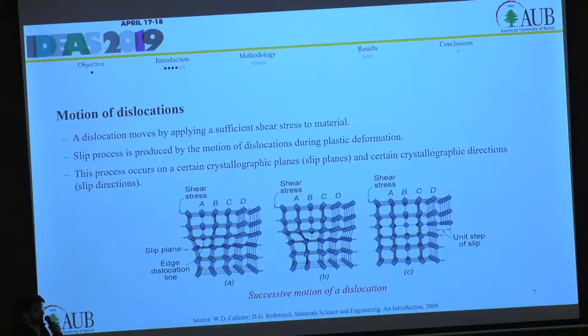And this process is called the slip process, in which the dislocation, as we can see here, dislocation A can move after applying this shear stress from position A to B to C, and finally having an edge at the right surface. So this process also can occur on a certain slip plane and in a certain slip direction.